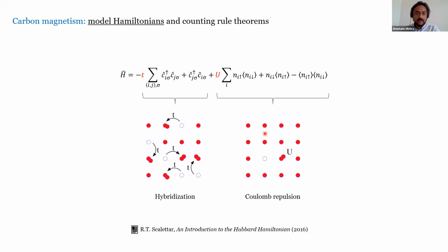So the model Hamiltonian that we will spend some effort towards is a very simple mean field Hubbard Hamiltonian, and that's mathematically shown on the topmost part and graphically on the bottom part. Essentially the first term is the nearest neighbor tight binding Hamiltonian, which promotes delocalization of electrons with a certain hopping amplitude T that depends on the extent of overlap of wave functions between different atomic sites. And the second term is a penalty term, the Coulomb repulsion, which goes through every site. And if it finds that one of the lattice sites is doubly occupied, necessarily with electrons of opposite spins, then it adds an extra Coulomb repulsion term.